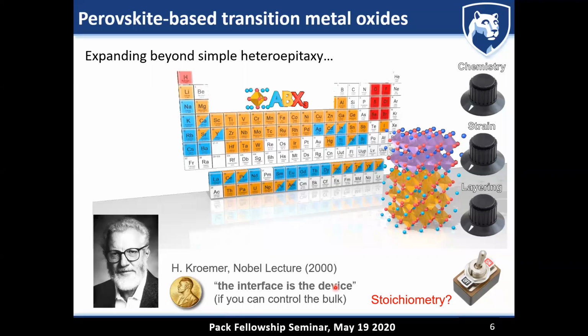the typical notion that when you're working with conventional semiconductors, the interface is the device. This is one of the famous sentences that Herbert Kroemer said during his Nobel lecture. And it's really true. The interface is the device because that's going to introduce the new functionalities. But really what you need to do is control your bulk stoichiometry to even be able to study what's going to emerge at the interface. And so for III-Vs, that's relatively easy to do. But for complex oxide materials, this is really going to be a challenge.